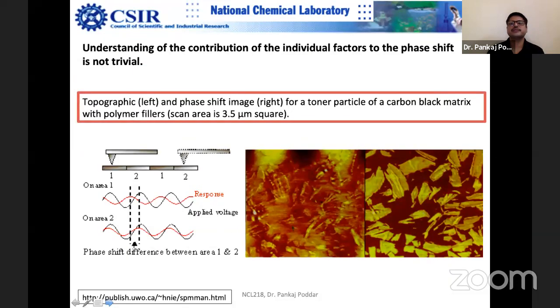There are some examples you can browse later on. This is carbon black matrix with polymer fillers. You can see this topography image and this phase image. The phase image gives you a lot of rich information in comparison to the topography image. And this is